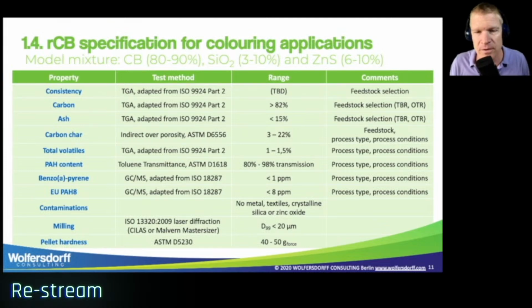In our case, we'll get to that. That might be either an internal mixer, or that might be a twin screw extruder. And if we don't disperse the recovered carbon black, we cannot get any color performance. That counts for plastics as well as for rubber processes.